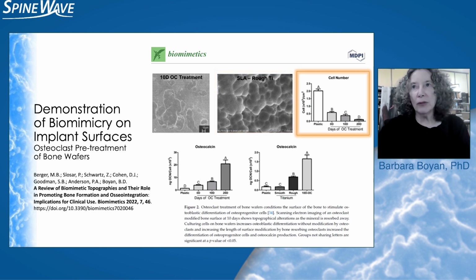So if you look over at this graph, you can see as longer that we etch that bone surface with the osteoclasts, that the cells, this is always our control. It's tissue culture polystyrene or plastic, because you can't see through bone and you can't see through titanium. So this is what they do on tissue culture polystyrene. They love to grow on tissue culture polystyrene, but they don't become osteoblasts very readily. But when we move them onto the osteoclast resorbed surface, the numbers of cells go down.